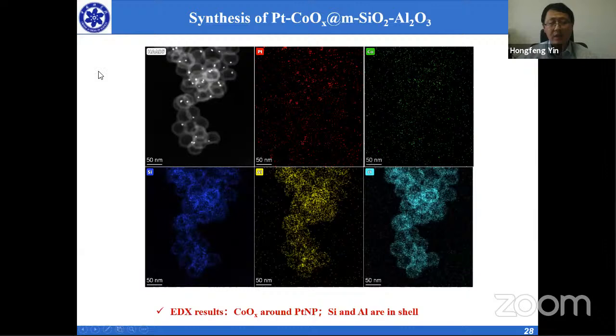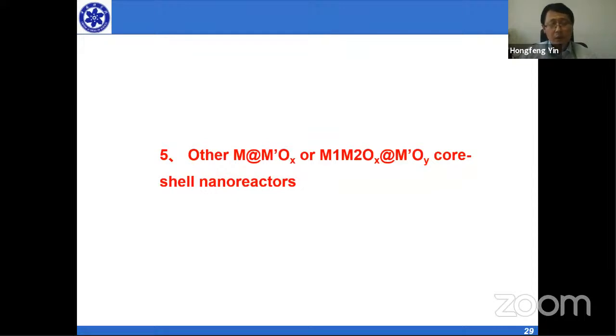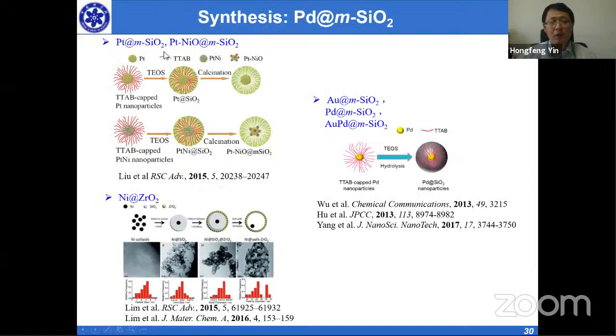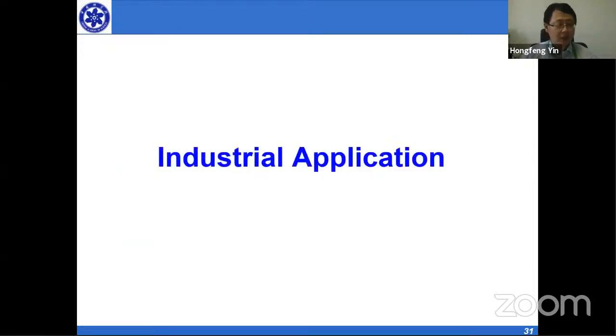This is the mapping of this structure. For silica and alumina, we can see that these two elements are at the same position, which means it is a uniform structure. And the platinum and the cobalt are at the same position. That means it has a good interaction. Besides all the previous work we have done, we also did other metals or metal oxides as a core, and other oxides as the shells. For example, we use palladium or platinum nickel oxide as core and mesoporous silica as shell, and nickel as core with zirconia as shell, or gold palladium alloy as core. So that's the work we have done.